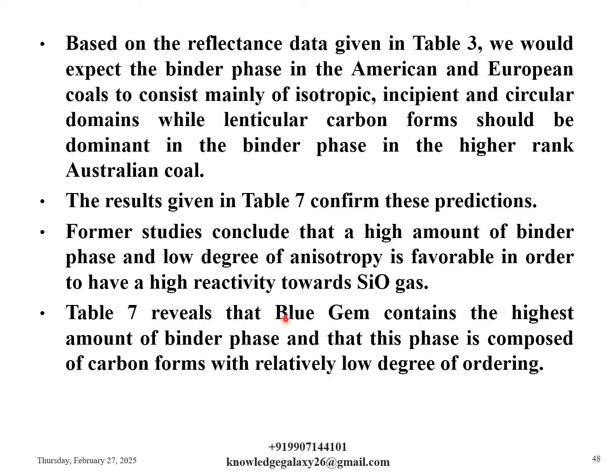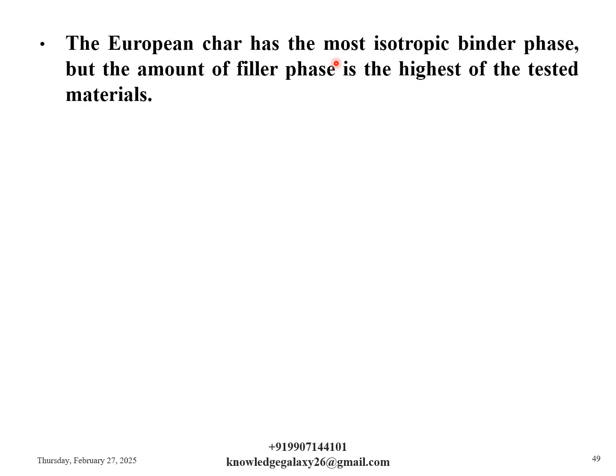Table 7 reveals that blue gem contains the highest amount of binder phase and that this phase is composed of carbon forms with relatively low degree of ordering. The European char has the most isotropic binder phase, but the amount of filler phase is the highest of the tested materials. The most striking observation from table 7 is the high amount of depositional carbon that is pyrolytic and spherulitic in the blue gem char.